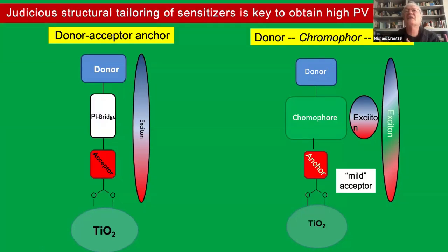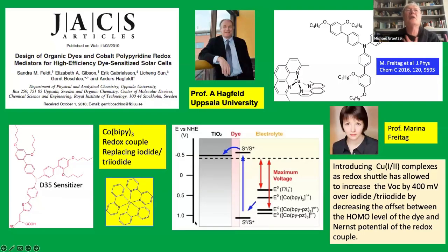There are many variants, but here I mention the pioneering work, I should say, of Anders Hagfeldt, but also Professor Marina Freitag. She actually came up with a copper complex that is really an ideal match for the sensitizers we are showing here. And so the energy loss in this regeneration step of the sensitizer is very small, 100 millielectron volts compared to 500 millielectron volts in the iodide case. And so that has driven the efficiencies up and also promoted the commercial application of these systems.